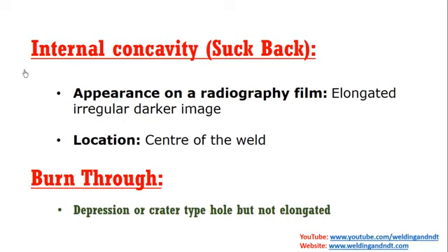Now internal concavity. There are two terms. One is internal concavity and the second one is burn through. These two are very different terms, but I have taken them in one slide because burn through is a spot-like defect. At one place there will be a burn through, and internal concavity will have some length.